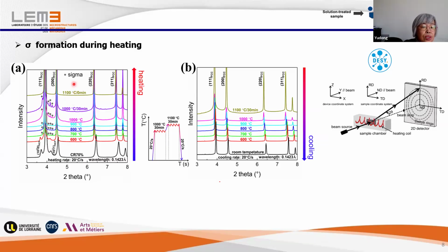These peaks correspond to the so-called sigma phase. They intensify with the increase of the temperature and reach the maximum at 1000 degrees C after half an hour of annealing. Then when we continue to increase to 1100 degrees C, these peaks disappear. Then when we cool, we see in the spectra here only FCC phase. When the material re-experiences the temperature range for sigma formation, we did not have the sigma phase.